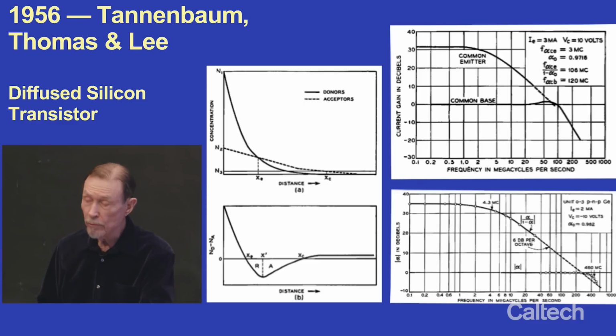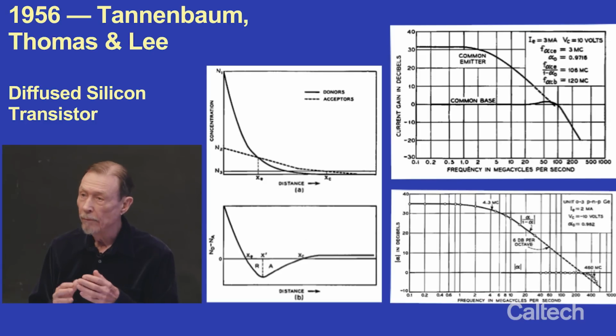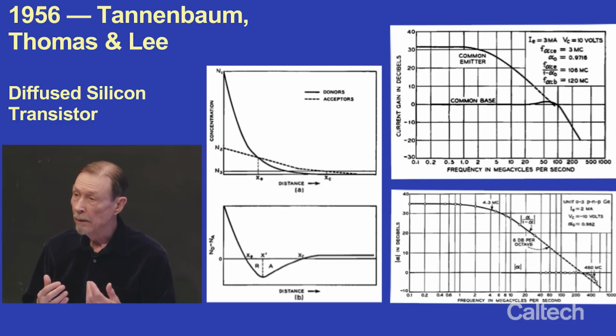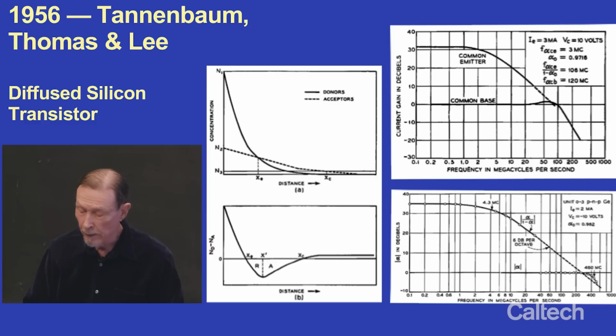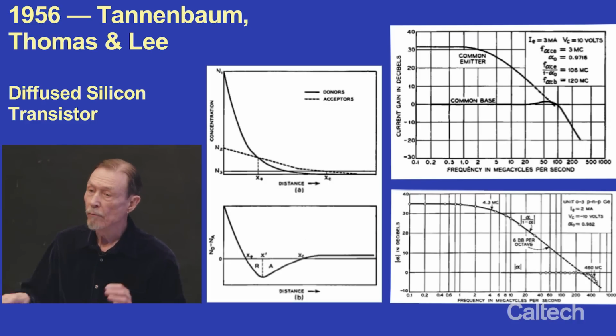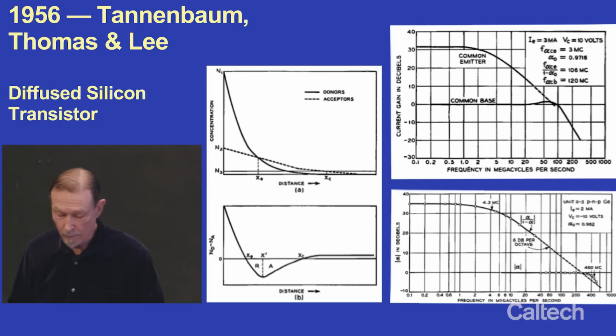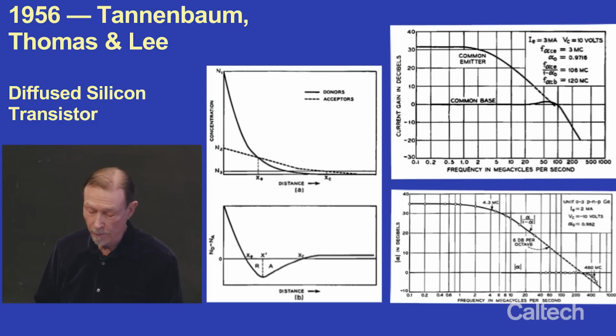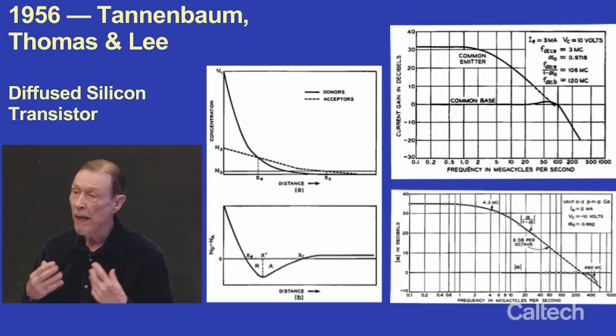And if you diffuse things in right, you could diffuse one kind of dopant in a short distance and then diffuse another kind in a longer distance. In this case, you started with a low concentration of N-type material, and then you diffused N-type material in, but you also diffused in a P-type material that diffused faster. So what you got was the bottom left picture there. The net doping, the net concentration of impurities, was N-type near the surface, N-type far in, and P-type in the middle. That was an NPN transistor.